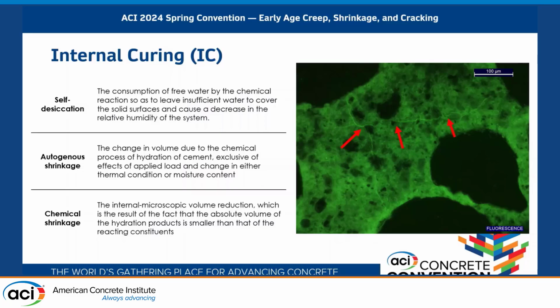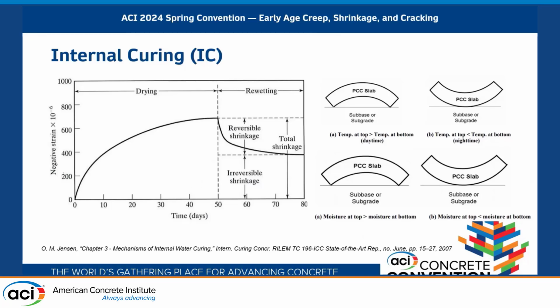The lighting isn't great here, but I hope it can be seen in this photograph where the red arrows are pointing at a crack that runs horizontally and also vertically. That is attributed to self-desiccation of a cementitious system where the water available was insufficient. We're going to talk a little bit about autogenous shrinkage, the volume changes that the material has from its own reaction processes, and chemical shrinkage, which is basically a microscopic volume reduction just because of what I said earlier, that the hydration products occupy a smaller volume than the unhydrated portion or unhydrated state.